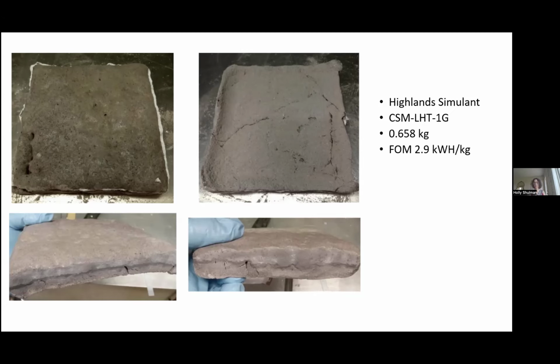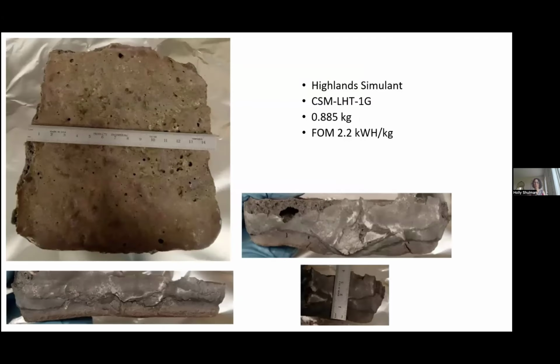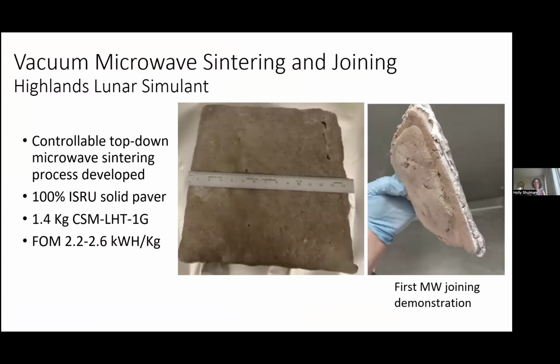And so, well over a half a kilo, and still even larger depth, better figure of merit. And finally, this piece, this was a small designed experiment. Finally, we got to a stage where we've got 1.4 kilos, which is pretty good size. It's got good thickness, it's got a good figure of merit. So I'm starting to develop a process that's working. Now I'm just recently cutting these apart and doing measurements, so I don't have that data yet, but this is looking good, like a solid paver.